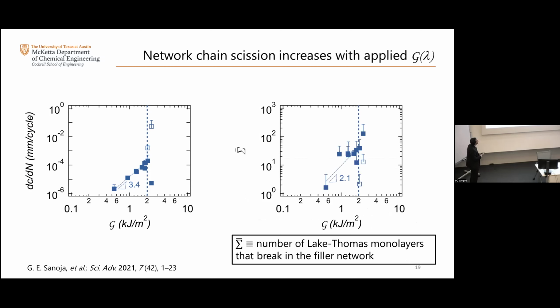So the first observation that we have is that, if our system actually fractured, this is our fatigue curve. So this is a macroscopic observation. And what you have here is the molecular damage. The molecular damage, we're defining as the number of Lake and Thomas monolayers that break. So we do some rescaling of our intensity. And effectively, what you have here at 1 is your Lake and Thomas limit. What we're showing here is that as you increase G, or as you increase the stretch at which you cycle your system until fracture, you break more monolayers of polymer chains in order to propagate the crack. So this is direct evidence that the Lake and Thomas model that has been around since the 1960s is insufficient and incomplete to describe the amount of energy that you dissipate by network chain scission. Because you don't only break 1 monolayer, you can break up to 100 monolayers of polymer chains before you propagate that crack. And that number of monolayers that you break is a function of the stretch that you apply during your cyclic load.